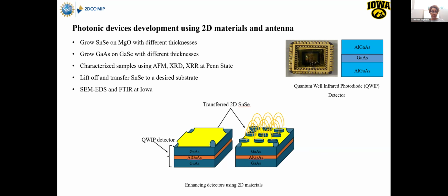So as a proof of concept, we start with tin selenide and gallium arsenide. So growing them, and characterizing them to make sure they have a good quality. And then at the end, we propose to lift off this tin selenide and transfer it to the desired substrate.